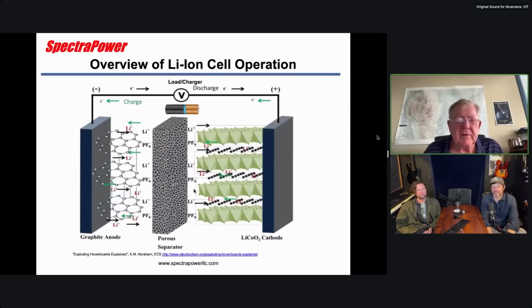The other thing that can happen is when you move the lithium, well, let me explain it, and then we can talk about it. So we build this cell. Let's start with a cell that we just built. It's discharged, so 0 volts. What we're going to do when we apply a charger, and that's what this little V shown up here is, is that all the lithium sitting in the cathode, we're going to apply a negative and a positive here, and cause the lithium ions to get pulled out of the cathode, and they're going to get moved back through the separator into the graphite.